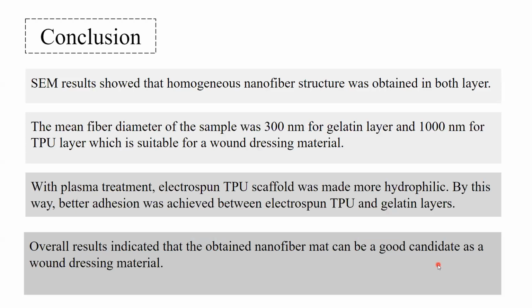To conclude, scanning electron microscopy results show that homogeneous nanofiber structure was obtained in both layers. The mean fiber diameter of the sample was 300 nanometer for gelatin layer and 1000 nanometer for TPU layer, which is suitable for a wound dressing material.